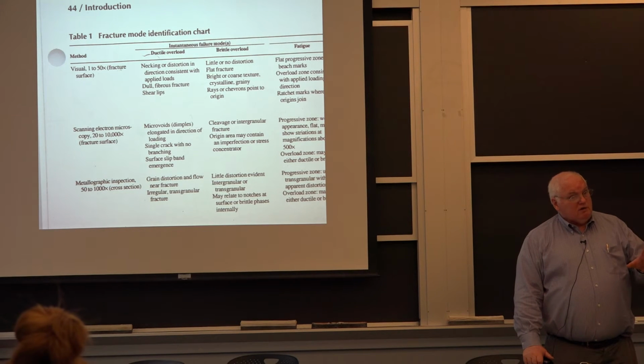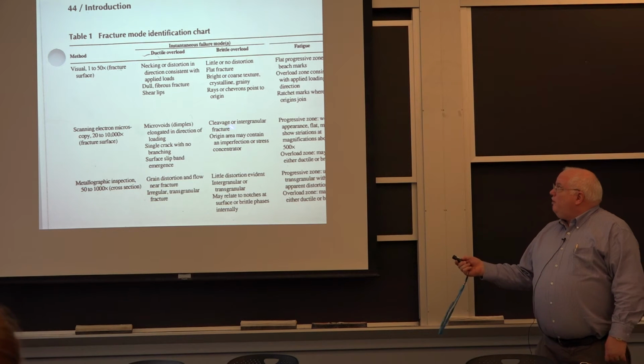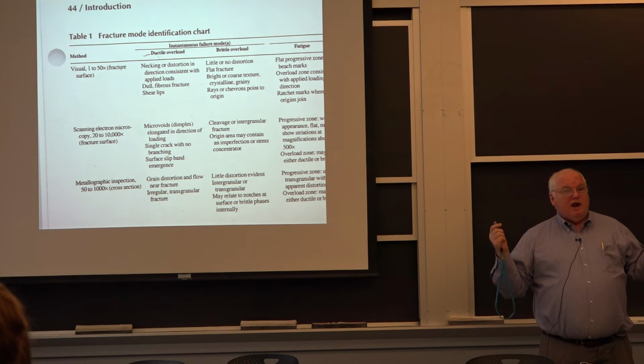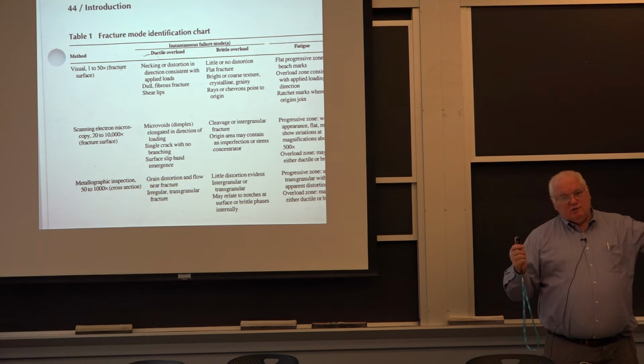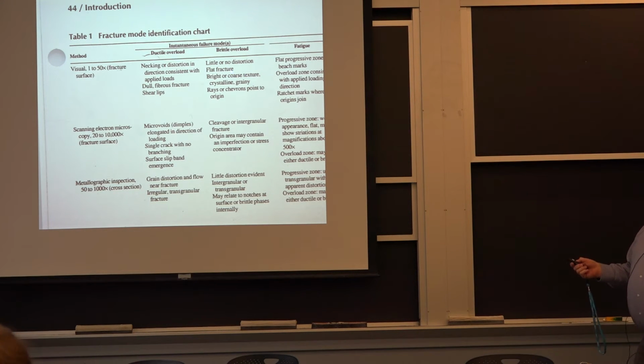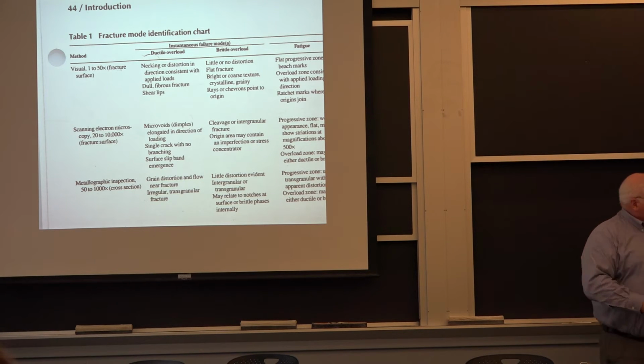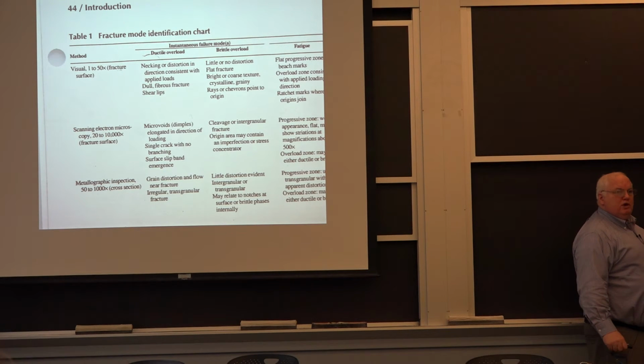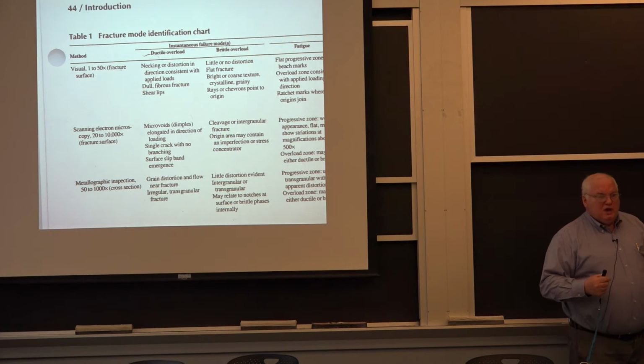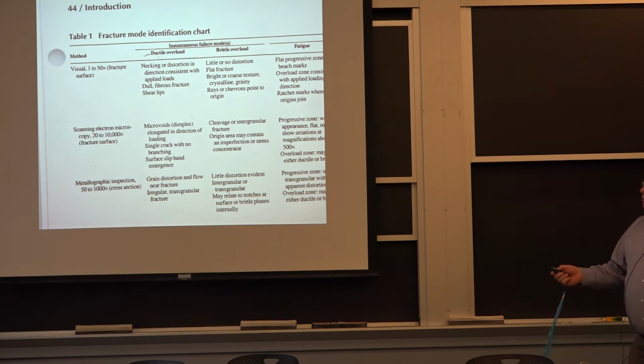So the steel was ductile. I knew right there. It was an overload failure. Okay? I didn't even have to go see it. I sent someone else to go look at it. But in any case, if it had been brittle and there had been no distortion, if it broke like a teacup so that you could glue it back together with crazy glue, that's brittle, and there is no way to predict the load it failed at unless you know the size of the flaw. In which case, I got to get in there and start measuring the fracture surface and look and see how big the flaw is. But if it's ductile, I don't need to know the size of the flaw.